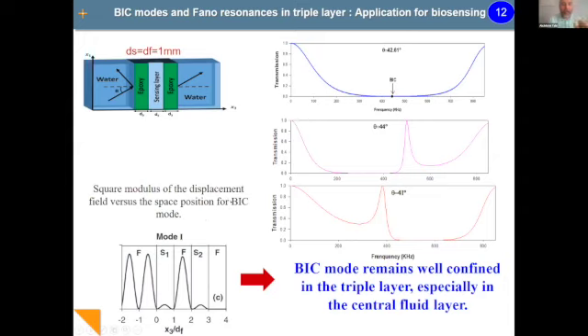If we look at the localization of the energy of this mode inside the structure, we will see that all the energy is localized inside the liquid, the central liquid layer. It means that if we change the properties of the sensing layer, of this liquid layer, we will change the position of the Fano resonance. We can also play on a lot of parameters: angle of incidence, the thickness of the layers, and other parameters. You can see here the response. The blue one is when we are exactly at the angle of incidence of the bound state, and then left and right of the bound state.